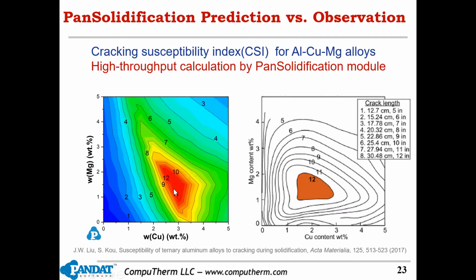As you can see, we predict the most vulnerable composition region is here. Basically, it's around 2 to 3% of copper and 1 to 2% of magnesium. This prediction agrees with the experimental observation very well, actually. And now we're trying to use this index to predict hot cracking susceptibility in multi-component alloy systems.